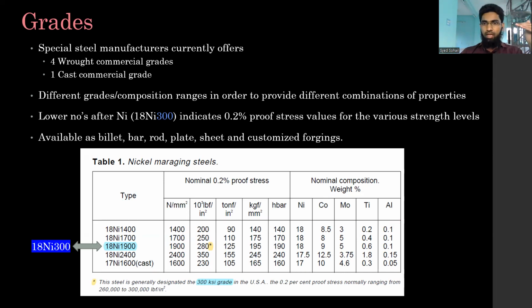Nickel, molybdenum, and titanium are to be maintained for an adequately high MS temperature. These three are set for achieving an adequately high MS temperature. Cobalt, on the other hand, doesn't directly contribute to increasing the martensite temperature or the strengthening mechanism. But what it does, it is added to compensate for the excess use of nickel, molybdenum, and titanium. And the overriding contribution is it doesn't allow the molybdenum to dissolve in the matrix. And what will that do? This will now make molybdenum available for intermetallic precipitates to form. So cobalt has an indirect contribution, is my point.